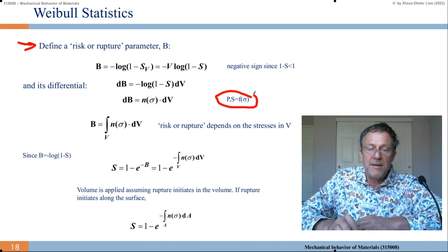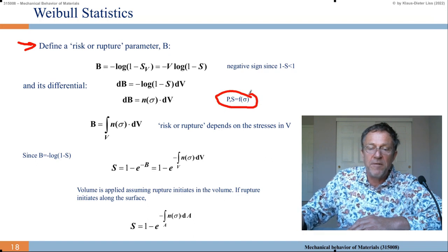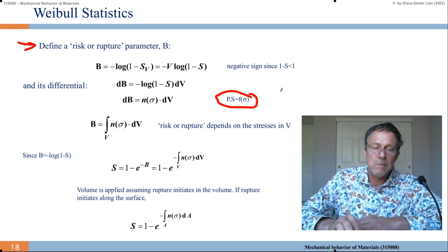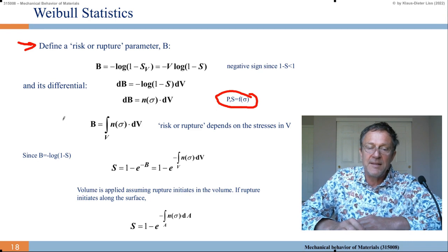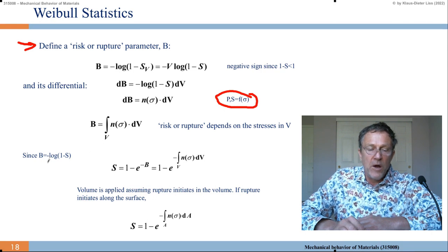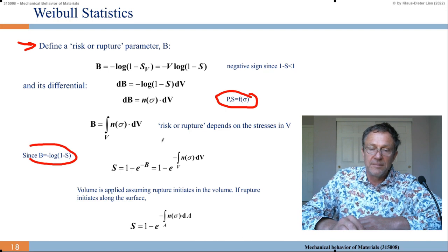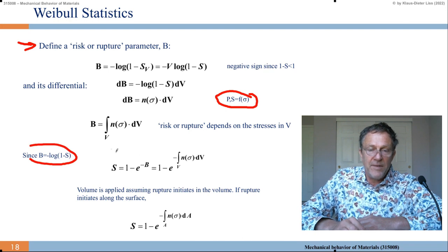But the probability for survival P and for failure S is a function f of sigma. Not the same function, but a function f of sigma. The one is 1 minus the other. Let's integrate it. So B becomes the integral over the volume of n of sigma times dV. Since B is that, then we get S equals 1 minus e to the minus B, equals 1 minus e to the minus the integral of n of sigma dV.